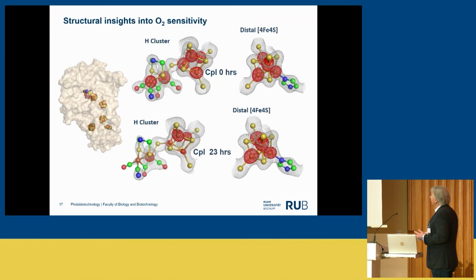With several methods, here I bring you the direct method. So we look at the structure of the cluster, and these red balls are the electron density of the iron atoms. If you have balls, then you still have an iron atom, and if not, you have no iron atom. You start the experiment without oxygen, and you see in the distal cluster, the electron relay cluster, you have a fully occupied cluster. The same is with the H cluster.